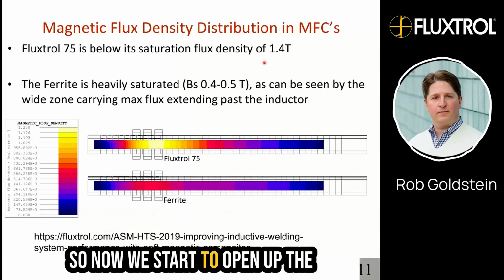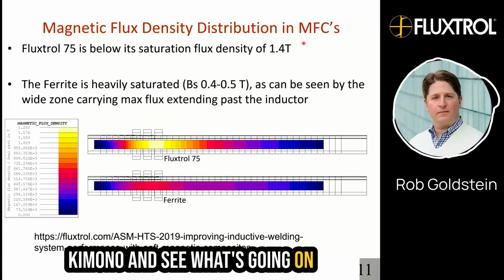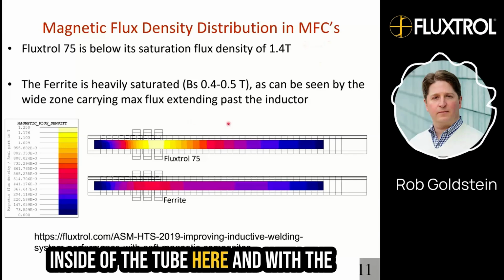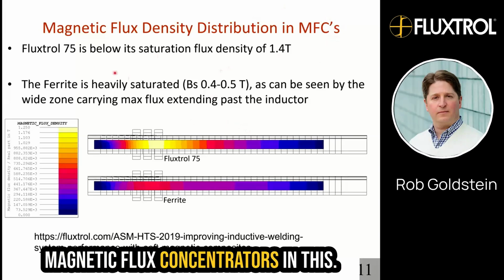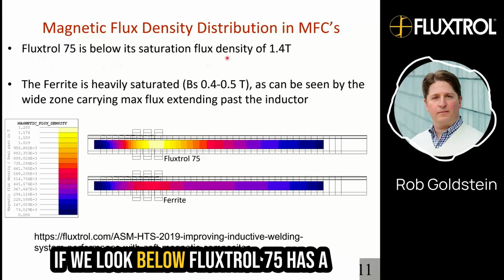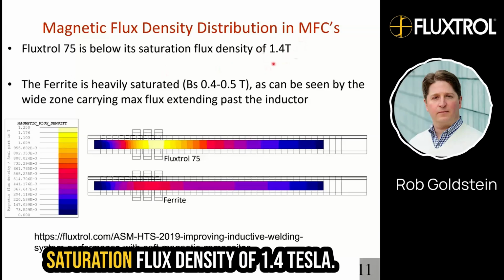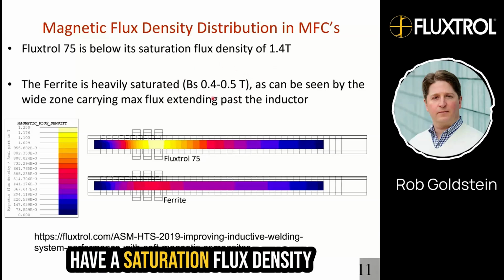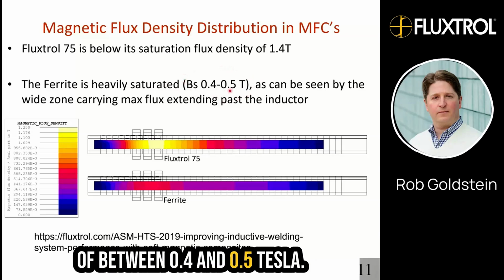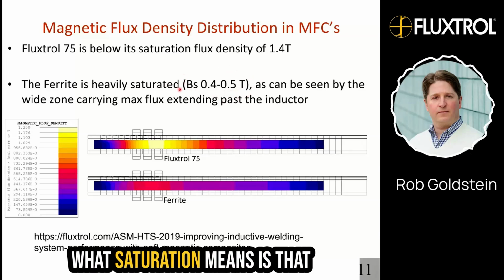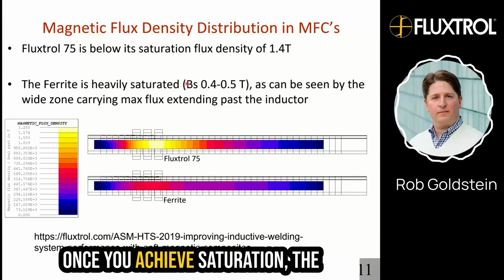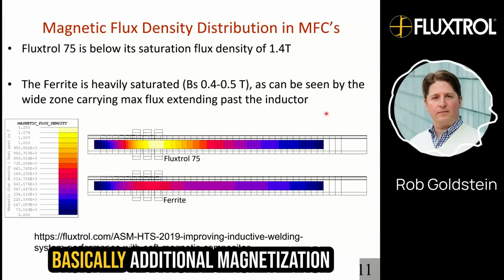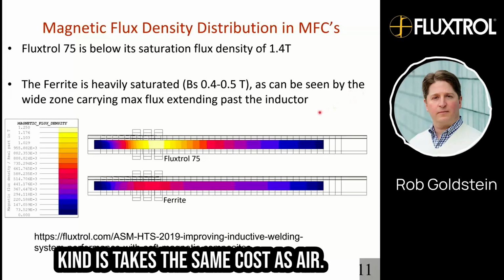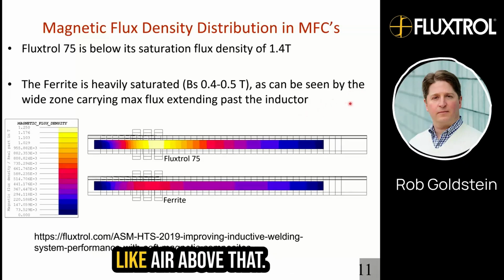So now we start to open up the kimono and see what's going on inside of the tube here and with the magnetic flux concentrators in this. If we look below, Fluxtrol 75 has a saturation flux density of 1.4 Tesla. Meanwhile, ferrites typically have a saturation flux density of between 0.4 and 0.5 Tesla. What saturation means is that once you achieve saturation, the additional magnetization basically takes the same cost as air. The material behaves like air above that.